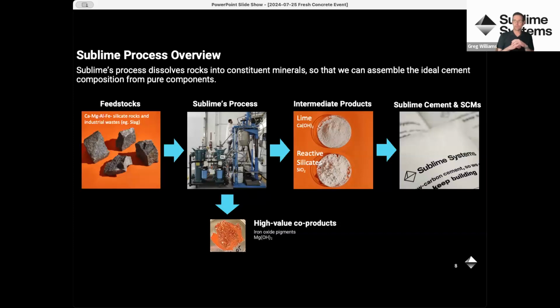Now, one other call out, we actually produce an excess of the silicates compared to what we need for just the cement. And so we intend to sell those silicates as a standalone SCM. They make a very performant reactive SCM, can be used similarly to a fly ash or a high-end natural pozzolan. So our philosophy is really use the whole rock. There's very little waste from the process, and we use the majority of the composition of the feedstock.